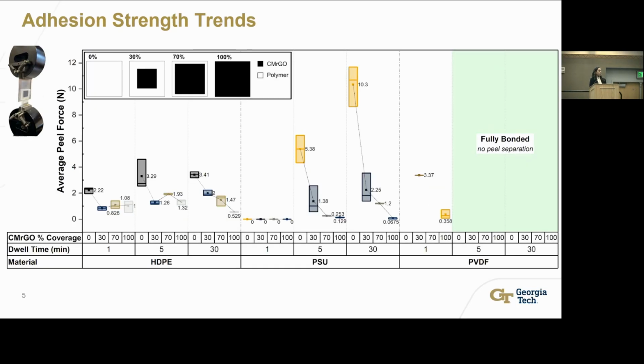Now I'll be moving on with our results, and here you're going to see the average peel force that is required to peel off our cap layer. And we're focusing on our different material groups at the bottom tier. We also have the manufacturing dwell time given in minutes, and this refers to the time that we are allowing our thermal lamination to happen. We also have respective CMRGO percent coverages that you can also see on the top left legend with the different percent coverages starting from no particles with 0% and up to a full CMRGO coverage